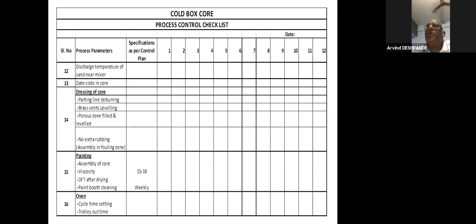Normally immediate tensile strength should be around 6. But if you maintain the temperature, same batch, same resin, same sand, it goes from 5.8 to around 7 or 7.4. So this is a marginal but good increase. That is the most important parameter, that's why I mentioned it: discharge temperature of sand near the mixer or discharge of the mixer.